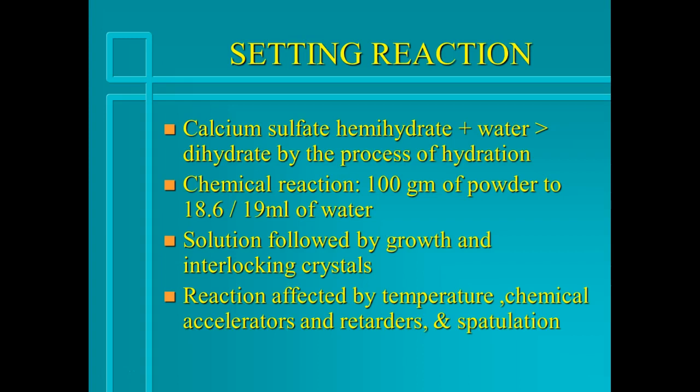Now, the chemical reaction with the gypsum stone occurs when 100 grams of powder is mixed with at least 19 milliliters of water. And that's very important for you to know. And the reaction is affected by temperature, chemical accelerators and retarders, and also spatulation.